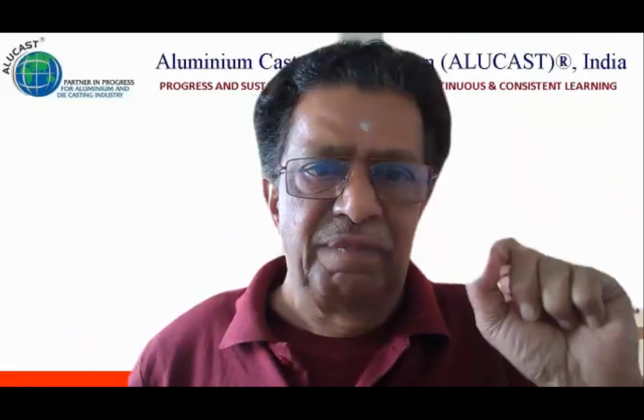Next question is from Mr. Jeevan Singh: how does Sn, Ti in alloy work as a modifier? Titanium, I'll tell you, is used as a grain refiner, not as a modifier to start with. We recommend titanium in GDC and LPDC around 0.05 to 0.15. And in field castings, we go up to 0.2%. That's the titanium. Tin, no. Tin is an impurity.